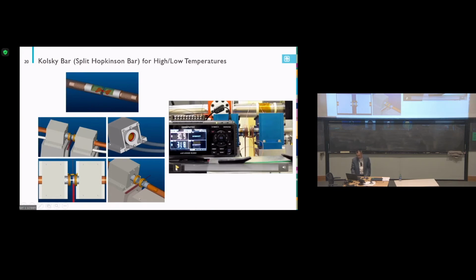Here you can see how fast they can heat the sample to 1,000 degrees C. So we run about 1,030 degrees C. You can see very fast it gets a glow, this orange color. It's very hot. So that's how we run the dynamic high temperature tensile test.